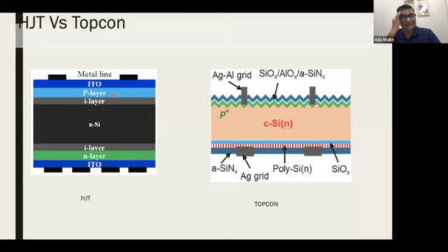No, okay. So these are not thick layers. These are only 5 nanometers. So that's the reason there would be a tunneling of the carrier through. So there is a physics behind it, so it is possible. Yeah. So I think there is a lot of band diagram physics which plays into it. But with this structure, you are able to move the carrier. I mean, the N layer is just on the crystalline silicon. This is an N plus layer, so it is not a junction. It is an N plus layer as a backside field layer. Okay, and this is a front side junction which is passivated with thin oxides.